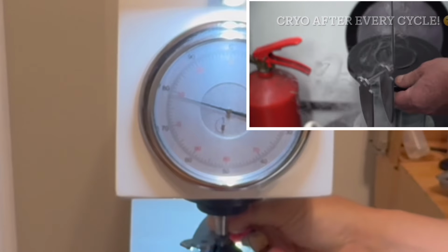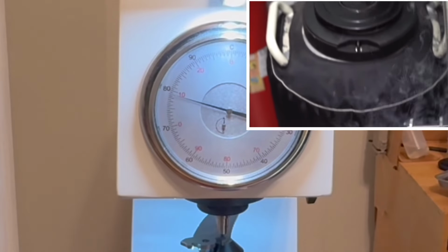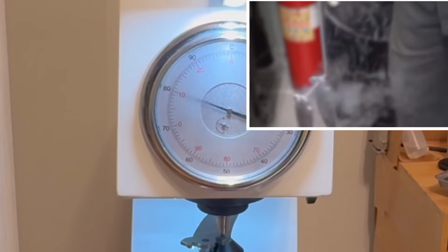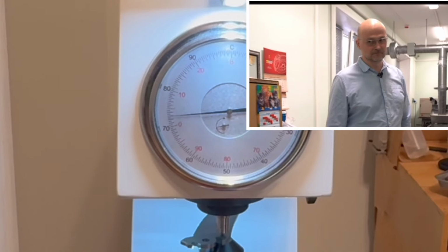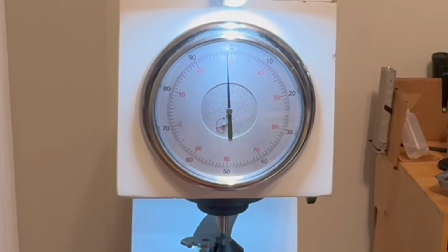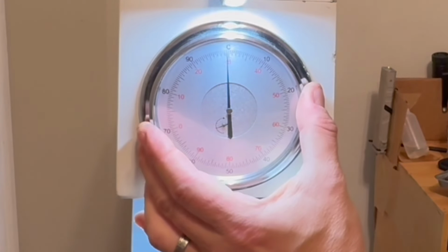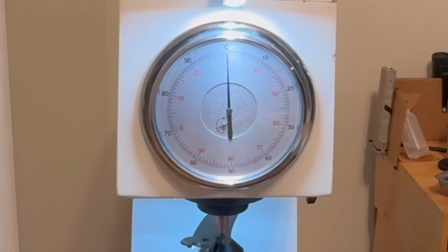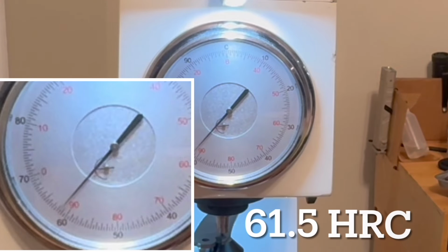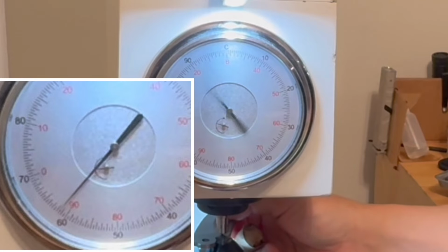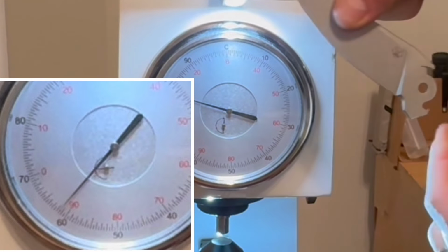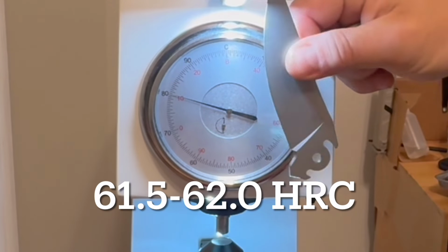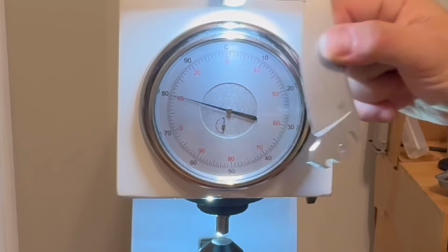Everyone knows that paper burns at 451 Fahrenheit, and so when it reaches austenitizing temperature of 1950 to 2050 Fahrenheit, there's no oxygen left and no residue of paper. It all burns out, which prevents decarburization of the steel itself, a common method amongst custom knife makers. 61.5 HRC on the final poke. So this particular blade is heat treated to 61.5 to 62 HRC.